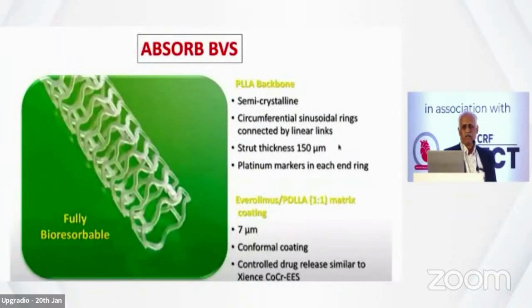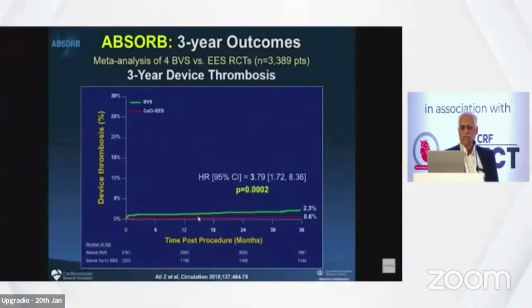So with these ideas, Abbott has come with the bioresorbable vascular scaffold, BVS. It is a semi-crystalline circumferential sinusoidal ring. Strut thickness is 150 microns. Because it's not a metal, it doesn't have enough radial strength. So this is a polymer. To give that enough radial strength, they have used 150 microns. And because it's not radio-opaque, you require markers at each end. And everolimus is the coated drug. This is the stent. The 3-year outcomes were not good.